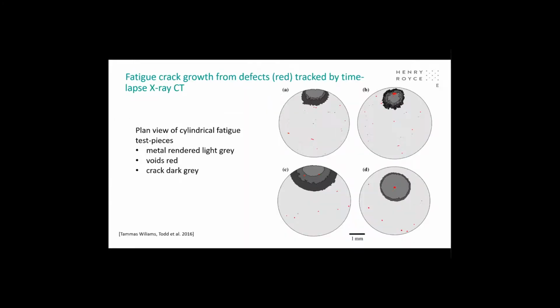We can study the nucleation and growth of defects, of cracks from defects. And here what we can see is a semi-transparent view looking down on 4 additively manufactured test pieces. What we can see here in red are the defects, the defect distribution in each of those 4 samples. We can see a number of defects, some near the surface and some at the center.